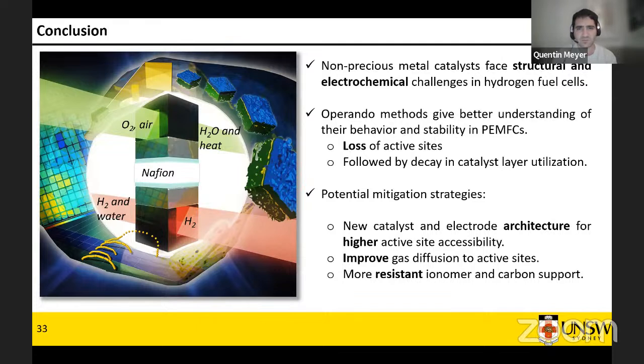Now, the second case is we want to get some more. So back to my catalyst, they're not behaving the same as platinum. And the operando method gives us a better understanding of what's happening. So first they lose active sites, and it's followed by decay in catalyst layer utilization. And the ways to mitigate it, there are 3 different ways at the moment. Some of it is what we do, some of it is more from the field. First one is you make a better catalyst to have higher active site accessibility, so more porous.